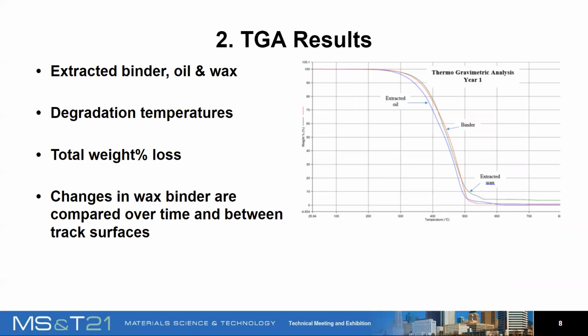Here in this graph, you can see the oil curve exhibits a steeper drop compared to the wax and other binders because of the oil's lighter molecular weight. The TGA can also help detect isomeric or molecular chemical changes, but higher and lower molecular weights may lead to a wider variance between the samples and may increase further as the hydrocarbons oxidize.